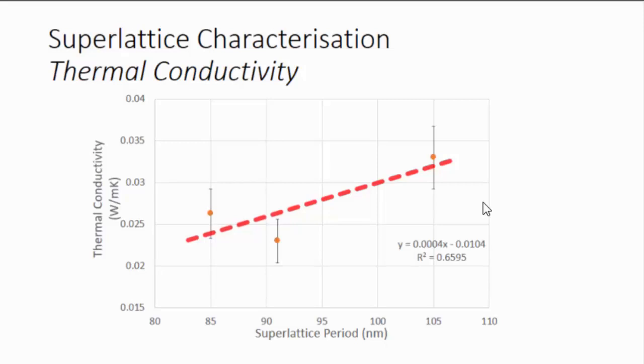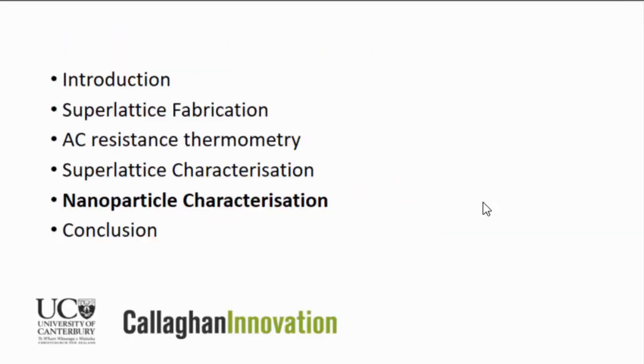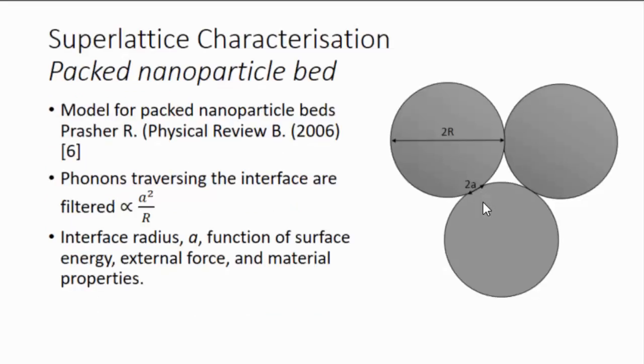So with this in mind, we started to seek out what might be the overall mechanism operating behind this thermal conductivity reduction. And we started evaluating it with respect to existing models. The one we eventually settled on and evaluated was a packed nanoparticle bed, so essentially evaluating the thermal conduction within one single nanoparticle layer. The basis of this is that for a phonon of certain frequency, trying to traverse from the body of one nanoparticle to the other, it has to funnel itself through this very small nanoconstriction here. And what you end up finding is that the phonons trying to traverse between 2 nanoparticles are filtered relative to the area of the nanoconstriction, relative to the body of the nanoparticle size itself.